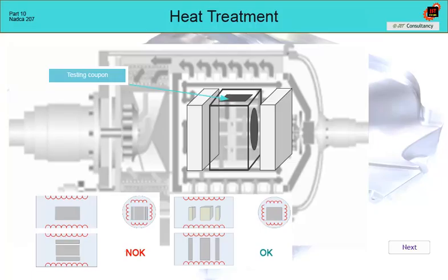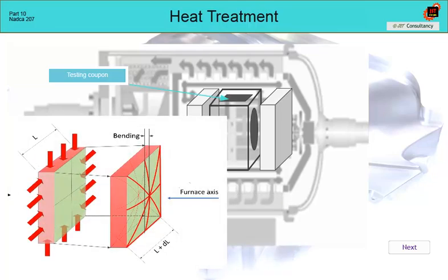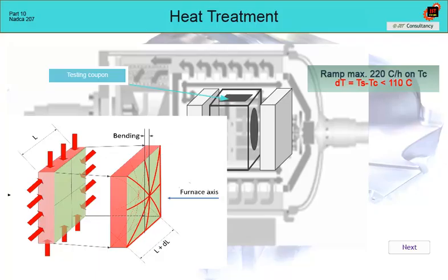It is only necessary to remember the heating rate. In this case, the outer part of the inserts heat up significantly faster than the core, which is why permanent deformation may occur. The heating rate must therefore be limited to 220 degrees Celsius per hour at the thermocouple TC. At the same time, the furnace software must be able to evaluate the delta T between TS and TC, and if it is greater than 110 degrees Celsius, the heating must be stopped to reduce the temperature difference.